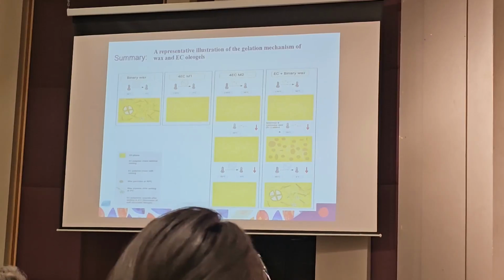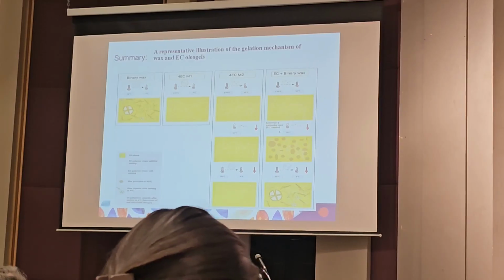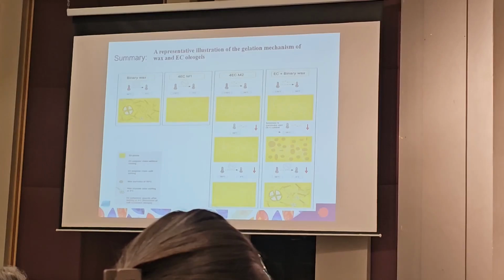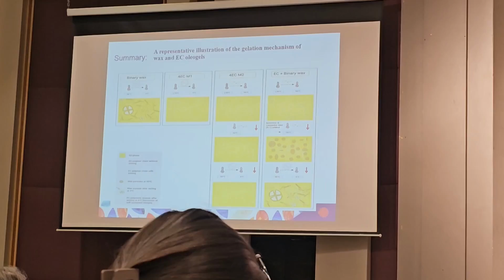Ethyl cellulose is like when you put gelatin in water, it dissolves completely. If we heat it to the right temperature, let's say 115 degrees C, when it cools down, it creates random structures, a three-dimensional network, and then it entraps oil, and we get this oleogel in here.